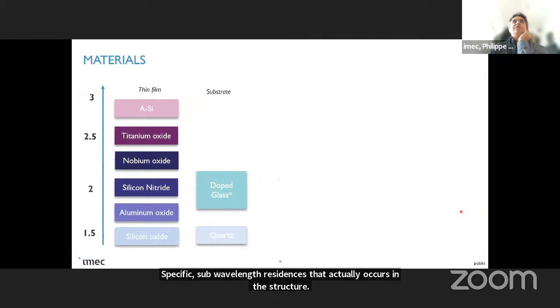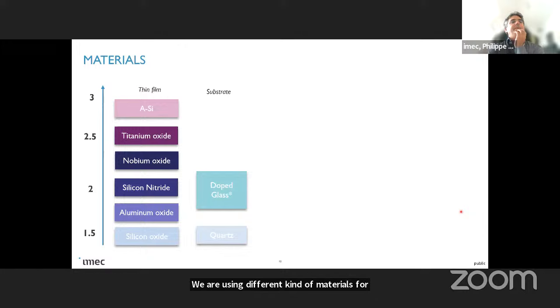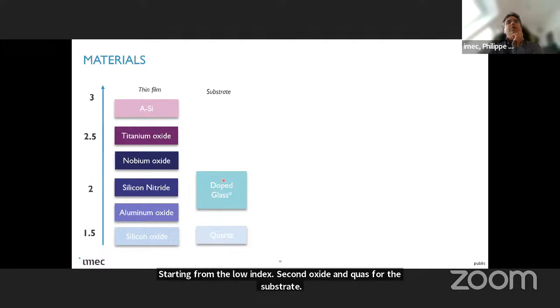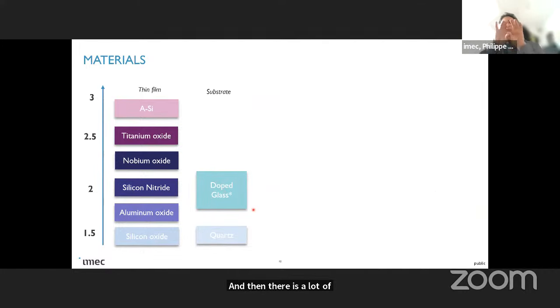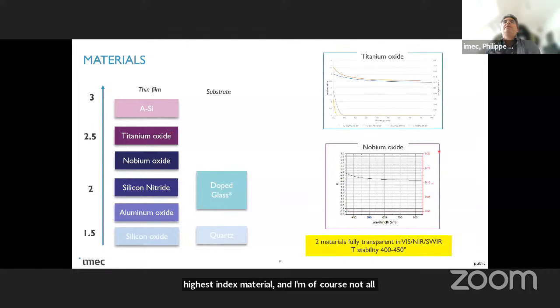We are using different kinds of materials for that, starting from the low index, silicon oxide and quartz for the substrate. And then there is a lot of work going on doped glass when you're actually using the core of the glass also as a waveguide. So that is very popular in AR/VR. But we are also looking into the highest index material, niobium oxide, titanium oxide, and even amorphous silicon. They are, of course, not all transparent in all the wavelengths, but that is what you need to do, for instance, when you are operating in SWIR or above 900.